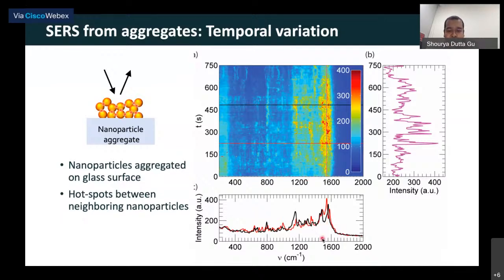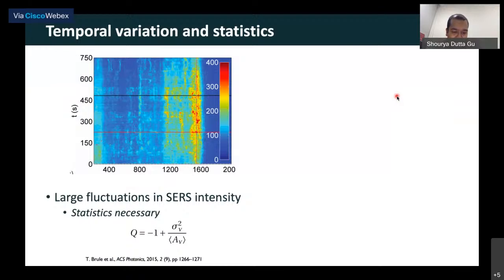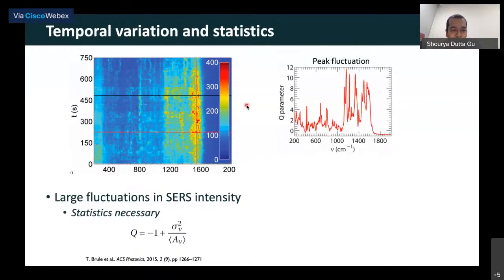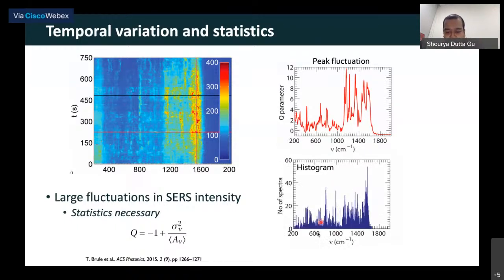Again, this is amplified if you look at a single wave number, in this case 1590, as a function of time that is shown here. And you see the intensity fluctuates significantly. So what do we do? What we do is a statistical analysis. So we look at a parameter called the Q parameter, which takes the variation of these peaks into account, and then we can plot that. And that is shown here. So from this whole data as a function of time, we can reduce it to a single spectrum that looks like this, which takes all the variations into account. And then we can see clearly all these peaks that we have in the Raman spectrum, and then we can use it for analysis. Or we can look at the histograms of the peaks and use that for different analysis, right?